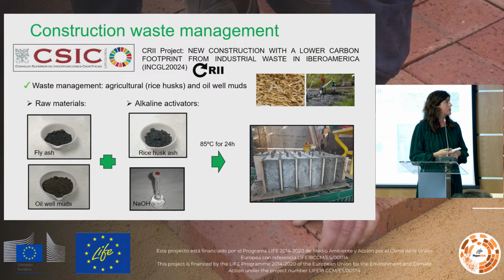In this other example, we have a project in which, I am in the team of this project, and we are using waste from Iberoamerica to build building materials with a low carbon footprint. In this case, the raw material is fly ash and oil well muds. As activators, we are using NaOH and also dissolving rice husk ash in this blend. We blended it, we cured it at 85 degrees for 24 hours, and we have obtained the material that you can see on screen.